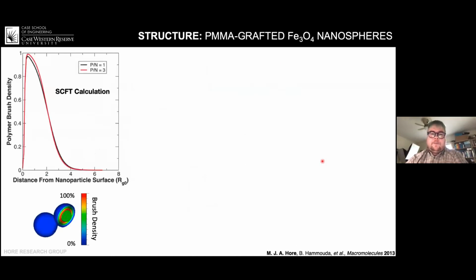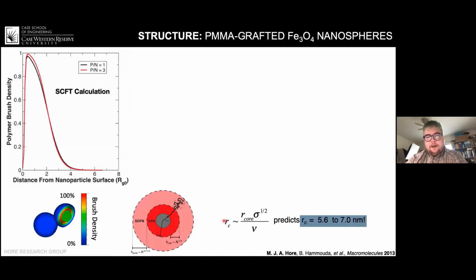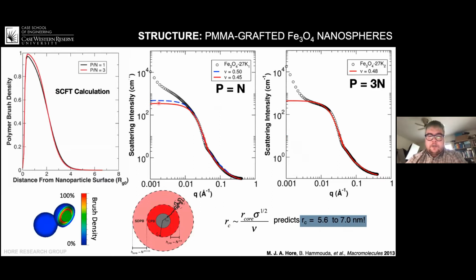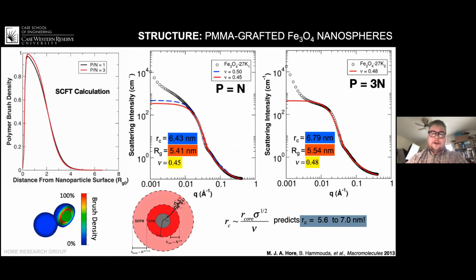All I want to do here is return to the original question, which was that the self-consistent field theory showed there was no appreciable difference in the density of the brush. The Daoud-Cotton model predicted that the cutoff distance between this concentrated region and the semi-dilute region was around 5.6 to 7 nanometers. And when we did the neutron scattering and fit with our model, which I'm showing in red here, we were able to not only get a good fit, but confirm that, first of all, according to nu here, this is the Flory exponent, the chains were roughly Gaussian. In blue here, this value of Rc, 6.5 nanometers, is exactly within the range of the Daoud-Cotton model. And the Rg of the polymer in the semi-dilute region didn't change much. So this brings everything together and unifies our picture of these polymer grafted nanoparticles directly.